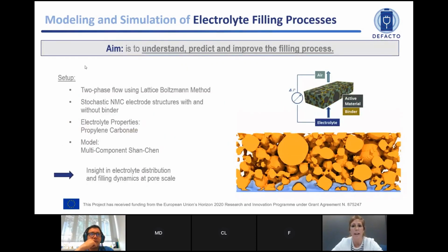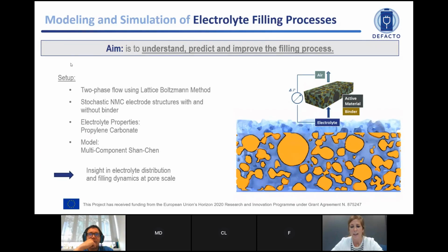Now, we proceed with the electrolyte filling process. Once we have the electrode, you need to proceed with several steps, and then once you build this, you assemble the cells, you need to fill with electrolyte. This step is a very critical step, both economically and electrochemically, basically because it is time consuming, and the wettability might also impact the premature degradation of the cell. So within DEFACTO, we will cover 2 scales and even different models to analyze the electrolyte filling process, starting from the mesoscale and then jumping to the cell level. So we will analyze pore level, electrode level, and then cell level as well.